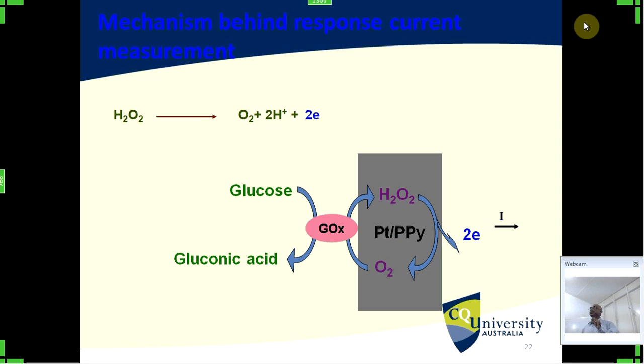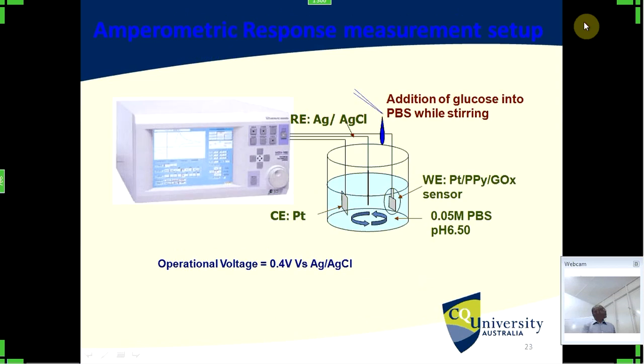Unfortunately, you cannot increase the sensor tip size because when it becomes bulky, it is inconvenient for the user to use. So the only way is improving the amount of glucose oxidase loaded into the same area. That's why we use this method, and this is the test setup, the electrochemical measurement system. Fabrication and measurement are both done by this system.